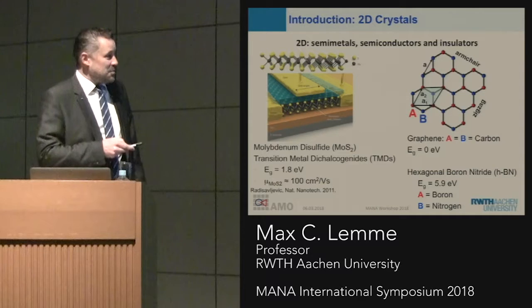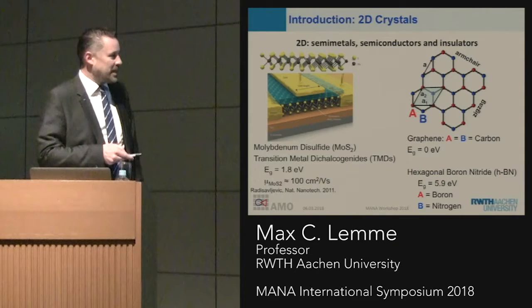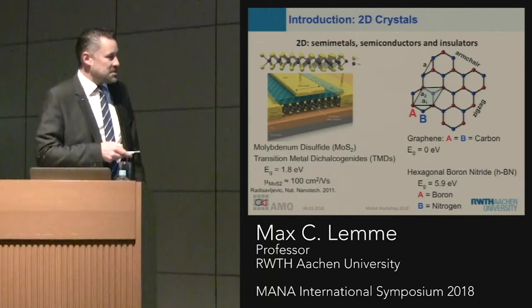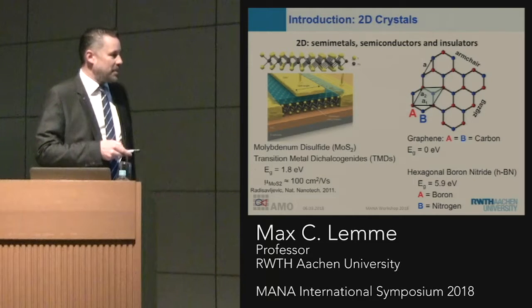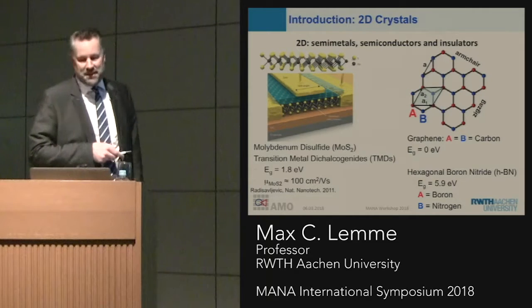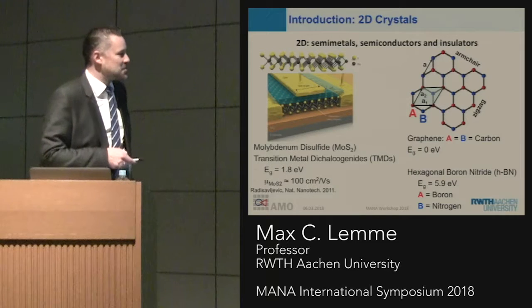If we replace A and B atoms with boron and nitrogen, we get hexagonal boron nitride, which is an insulator with a small band gap for an insulator of 5.9 eV.